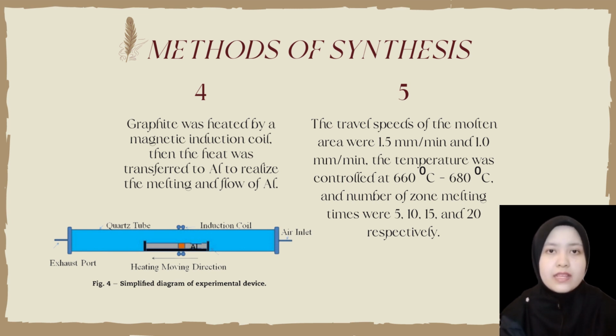In the experiments, the travel speeds of the molten area were 1.5 mm per minute and 1.0 mm per minute. The temperature was controlled at 660 degrees Celsius to 680 degrees Celsius, and the number of zone melting times were 5, 10, 15, and 20 respectively.